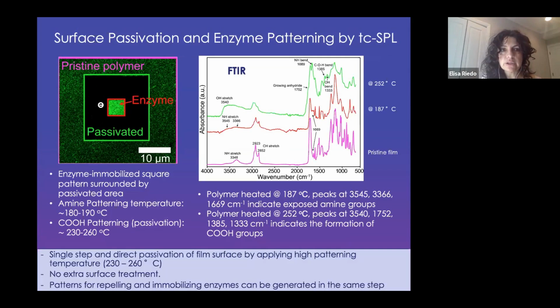This is a slide showing the surface passivation scheme. So here what you have is the pristine polymer, and as you can see, unfortunately, even if it is pristine, when you dip it in the solution with the enzyme, some of the enzyme will still attach to the polymer. Remember, these enzymes carry a very strong negative charge. So somehow the polymer is still attracting this enzyme. So the non-specific binding is quite elevated.